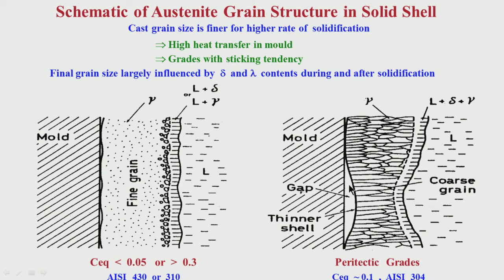Here in peritectic grades, friction is not an issue, here the issue is gap formation. Gap formation means the heat transfer is coming down. So, the powder characteristic and the slag characteristic will be such that this heat transfer has to be taken care of. Because of sticking, the friction has to be taken care of in the mold, and here because of the shrinkage tendency, this heat transfer has to be taken care of in the mold.